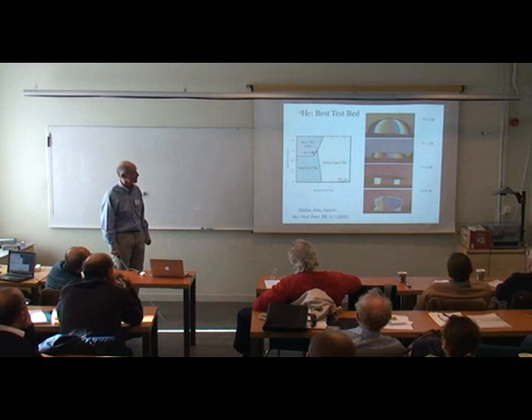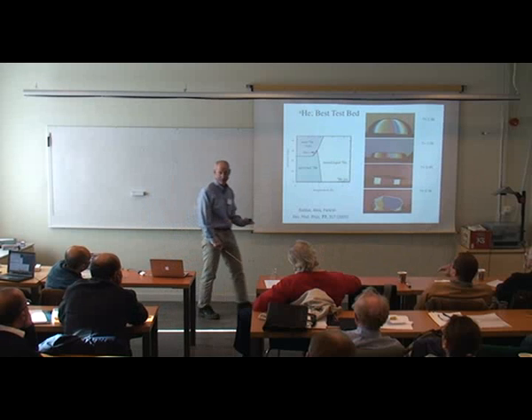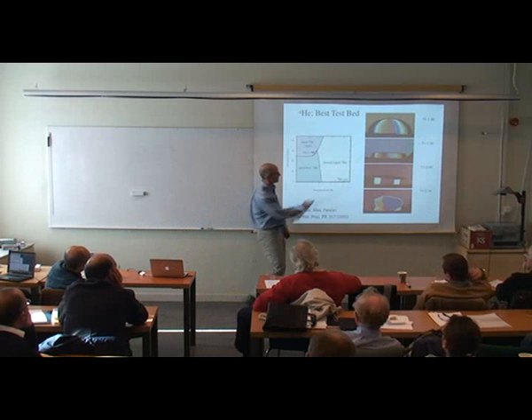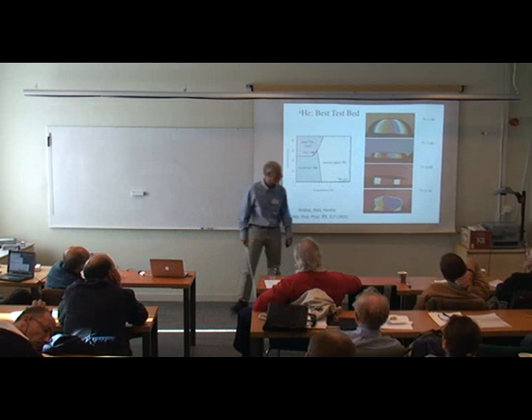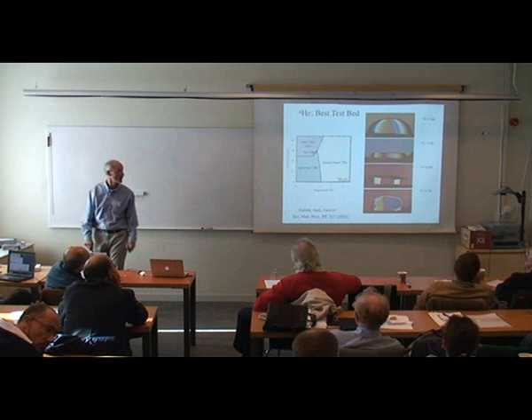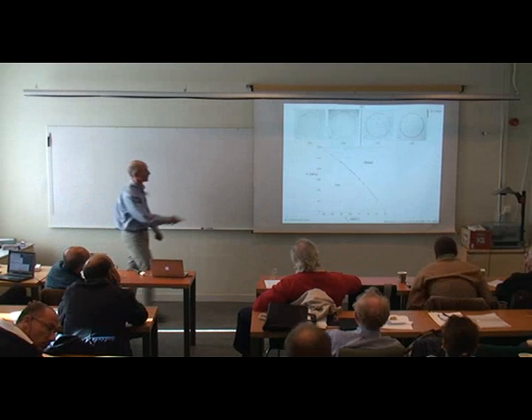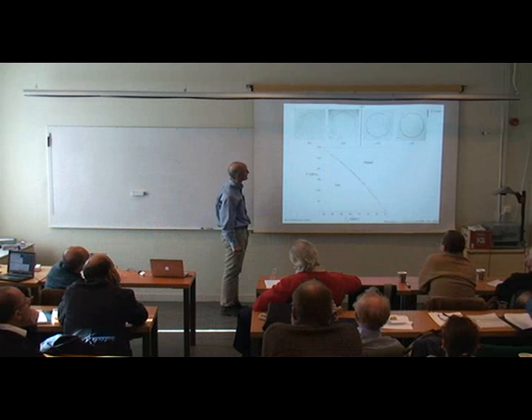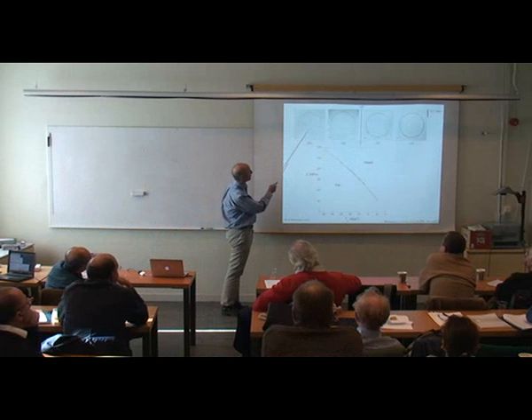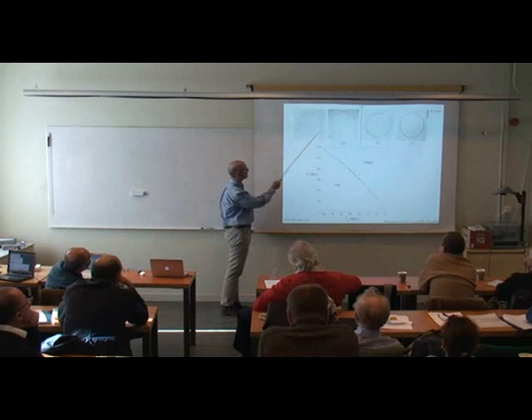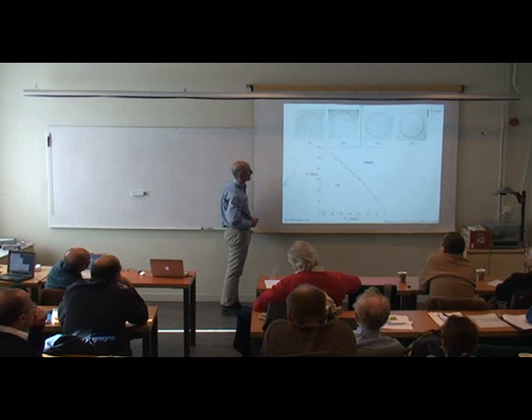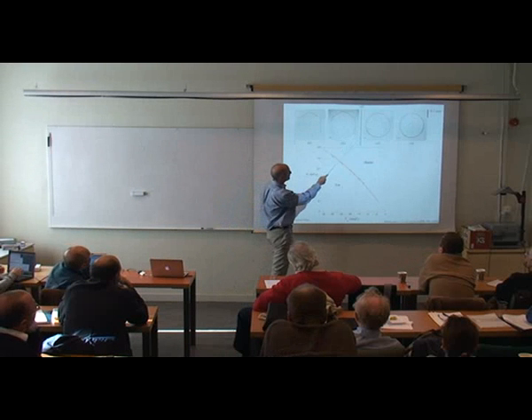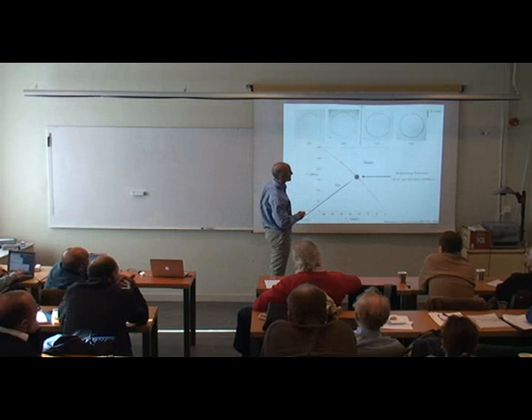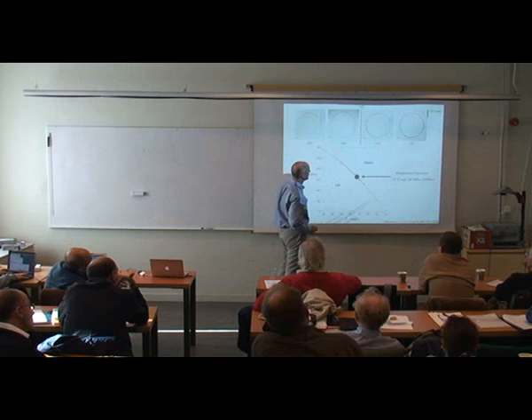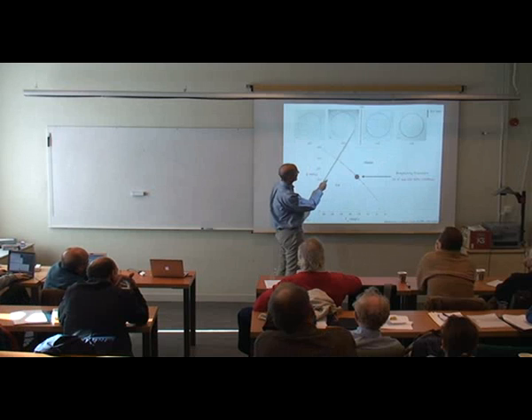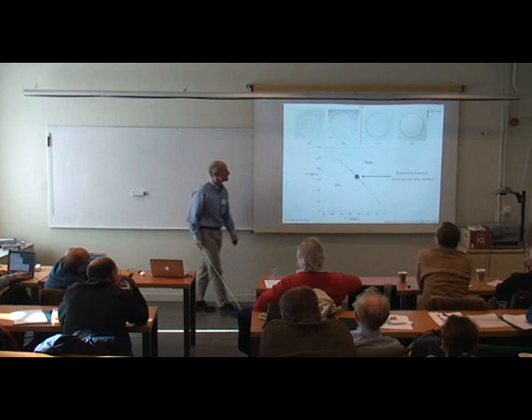Okay. So helium-4 is the test bed because you don't have to wait. Okay. If you don't know why, we can talk about it later. But you see, the crystal becomes much more polygonal as the temperature gets lower. Ice does it. This is looking down the c-axis of a single crystal of ice. And so this is the familiar hexagonal structure. These are literally facets. They're called the prism facet. And as you go above this temperature, you see at minus 16 degrees, 160 megapascals, this is ice and water, then this facet undergoes a roughening. Okay.